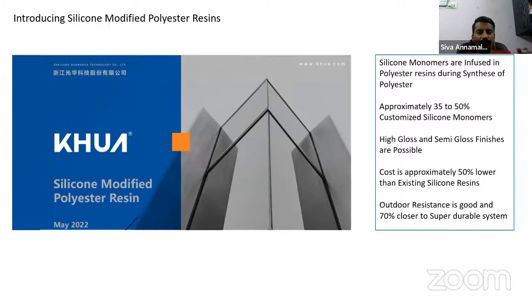What is this polyester? When you synthesize or manufacture polyester, specially customized silicone monomers are infused into the polyester chain at the time of manufacturing. It is not like a physical blend of two resins. It is basically special silicone monomers infused in polyester resins. The approximate ratio could vary from 35 to 50%. It means finally you get a polyester, but that polyester consists of silicone monomers to the tune of 35 to 50%.